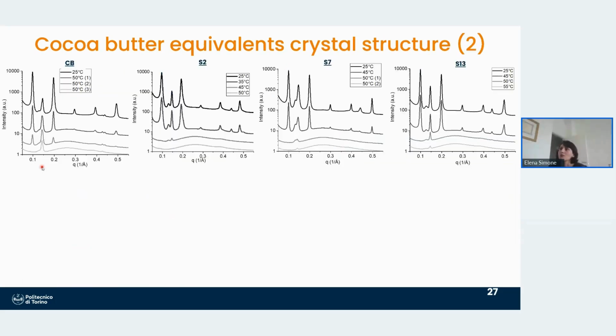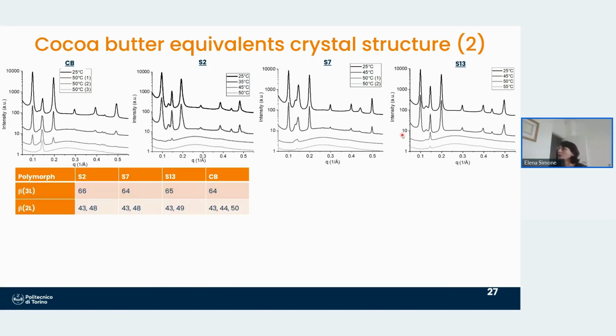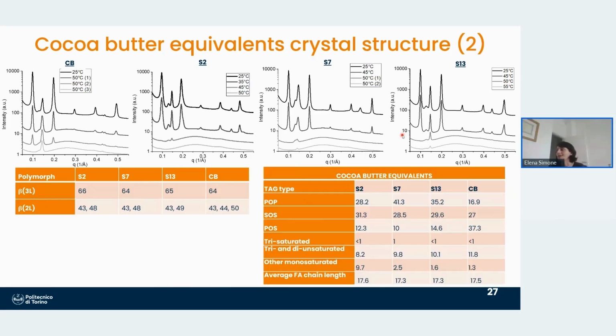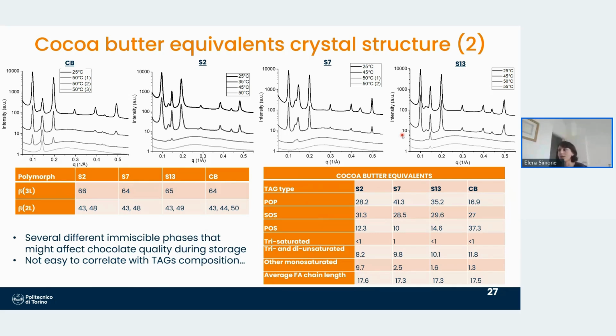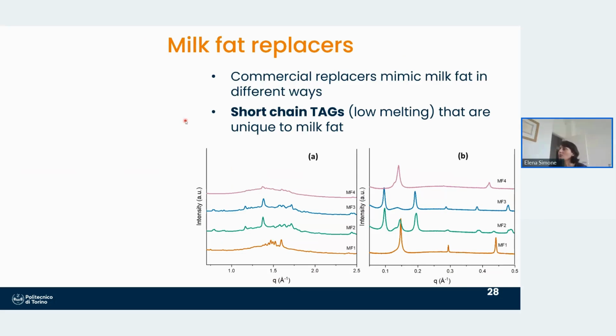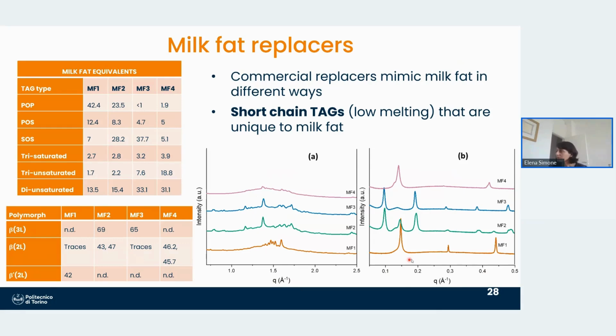So again, we measured many different compositions, and they are all different to the point that it's still a little bit unclear exactly what the correlation is between the TAG composition and the presence of these phases. So we're really working on a more rigorous thermodynamic approach, perhaps incorporating some machine learning elements. I'll just again go quickly with some fat replacers. As you can see here, different composition, different polymorphic landscape. And again, it can be a problem when you are trying to formulate a product.